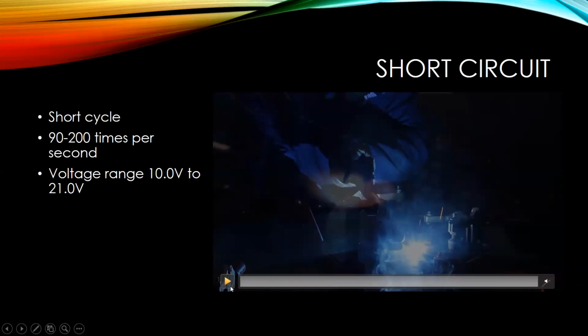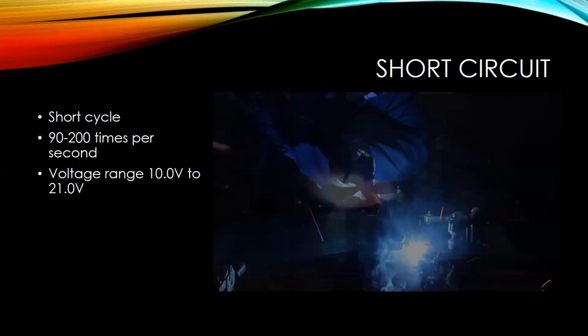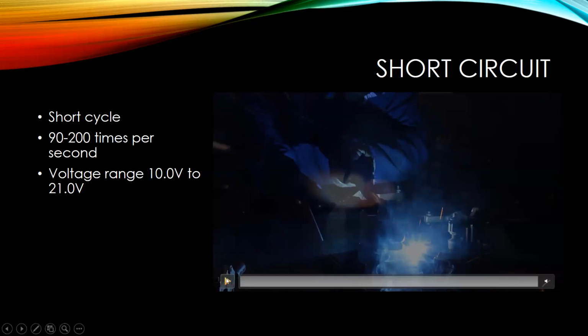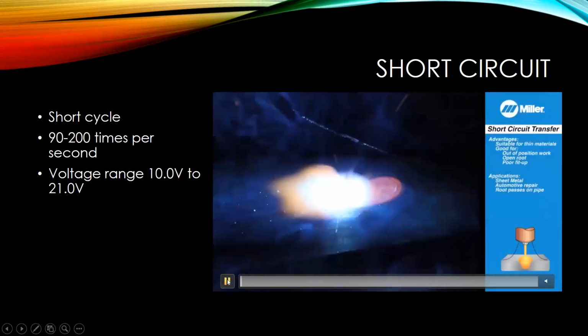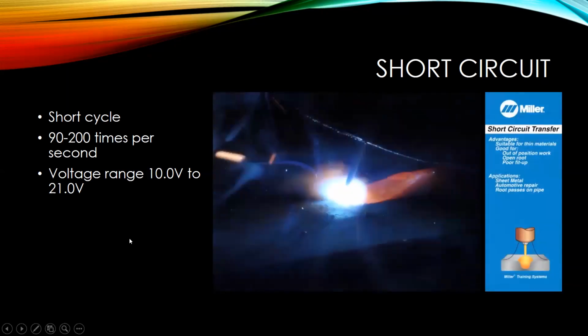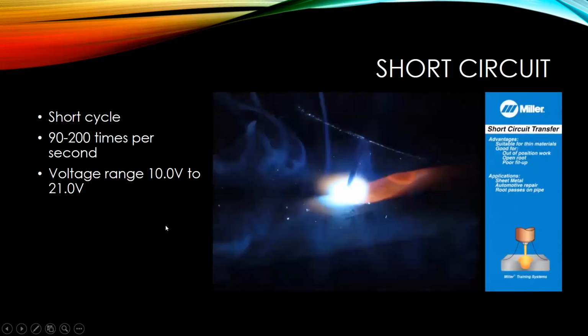And what you'll see is the wire is going to come down, make contact. The amperage is going to increase and clear the short because that wire's made contact. And then what you're going to see is the arc will stay on. Slight ball will grow. It's going to touch again, and you'll see that transfer. So there it is at a high speed. Now it's at a low speed. So you see that